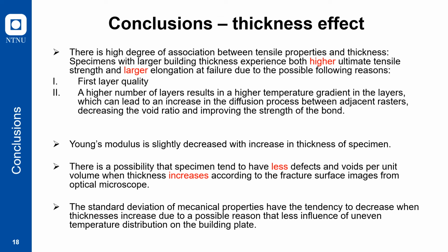And next, the higher number of layers can result in a higher temperature gradient in the layers, which can also lead to an increase in the diffusion process between adjacent layers. And this will result in decreasing the void ratio and improving the strength of the bond, which will improve the ultimate tensile strength as the thickness increases.